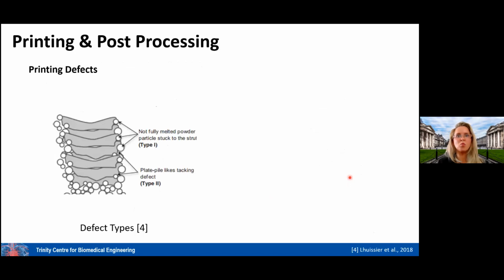So we had other issues to consider as well when it came to 3D printing, in that there are printing defects. The way that laser works, we end up with a lot of this debris or particles attached to our struts. And that can have a big impact on things like the surface finish, and on how it interacts with the artery. And it's really not possible to place a stent in that would have all of this debris or dross on the as-printed structure.